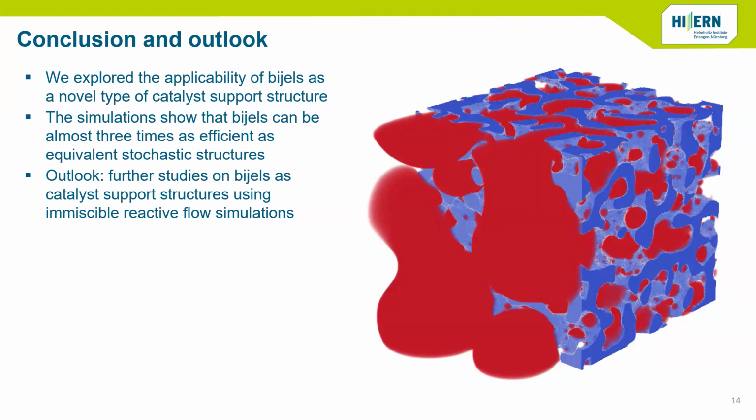I noticed you use contact angles that are away from 90 degrees. Does that affect the stability? The higher the contact angle, the lesser the stability, because in that case, the area that is covered by a particle at the interface is smaller, so the detachment energies are lower.